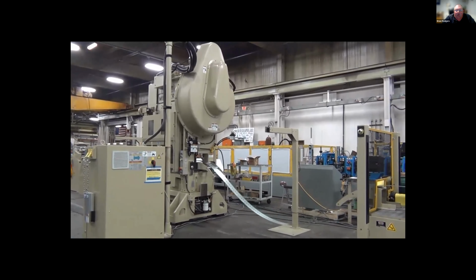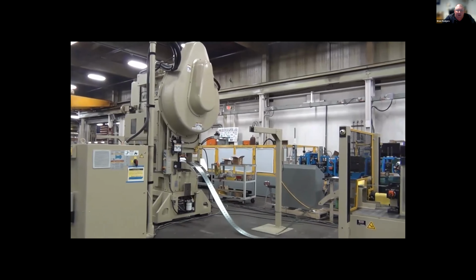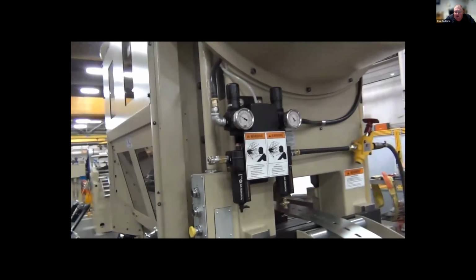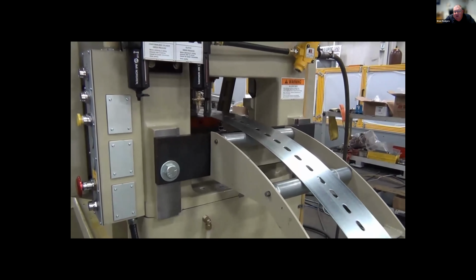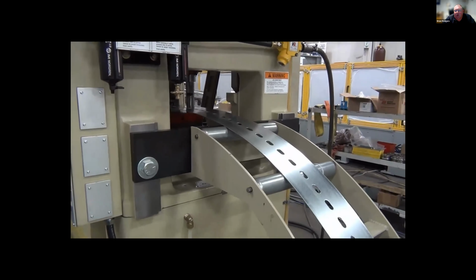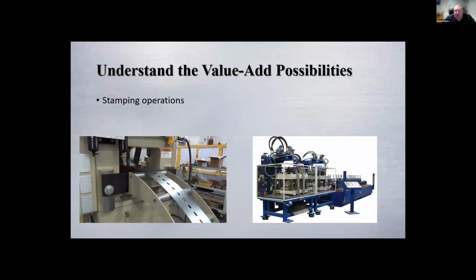This here is making a repeating pattern. This is at a slow rate of speed, but in actual reality, this line is pushing almost 200 feet a minute. It puts these holes in, it comes through. Trying to give you a better shot. You can see the stamping operation and the hole pattern that it's giving, and it has a set distance between each hole to the part print, and then it will go into the roll former. This other machine here on the right, this is another post notch operation where it is coming out of the roll former and some type of feature is being put in, and then the cutoff operation is happening next.